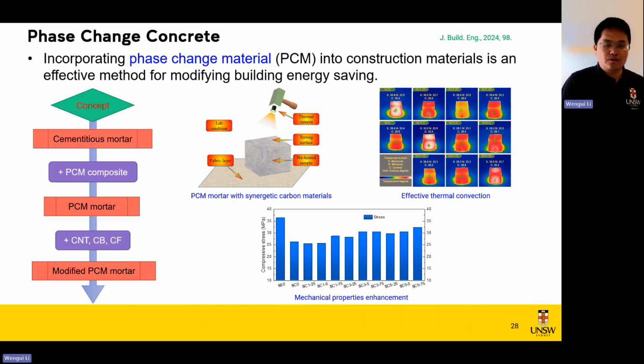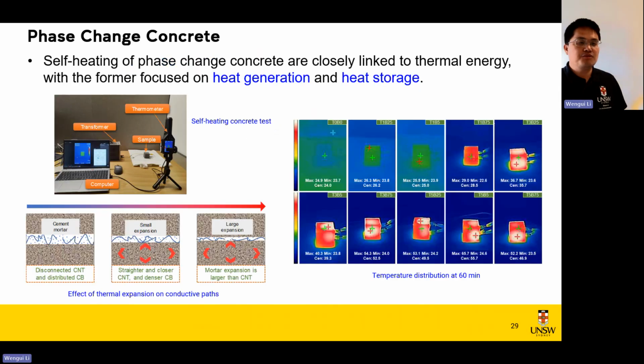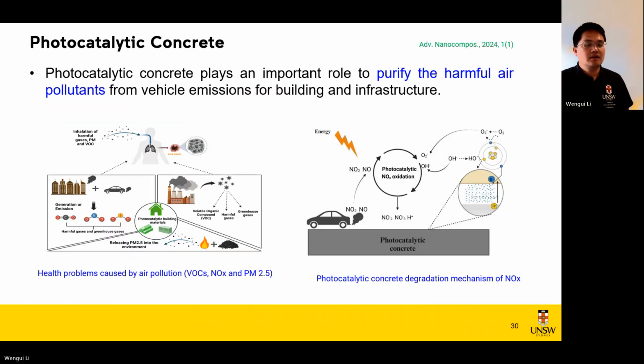But we found the carbon nanomaterials can improve the thermal energy saving and the performance of phase change concrete. And this is because the carbon nanomaterials establish excellent thermal conductions inside concrete. Now here we look at the self-heating performance of phase change concrete, focusing on the thermal energy generation and the storage. So basically, due to the excellent thermal and electric conductivities, carbon nanomaterials can improve the self-heating performance of phase change concrete. And also, we found there is optimal content of carbon nanomaterials to achieve the best self-heating performance for phase change concrete.